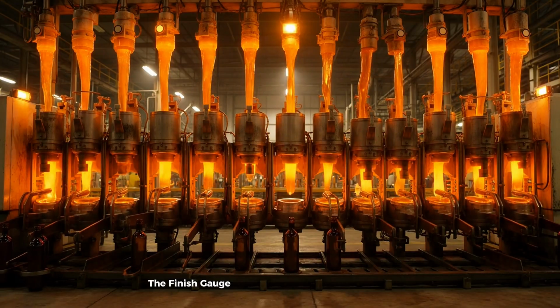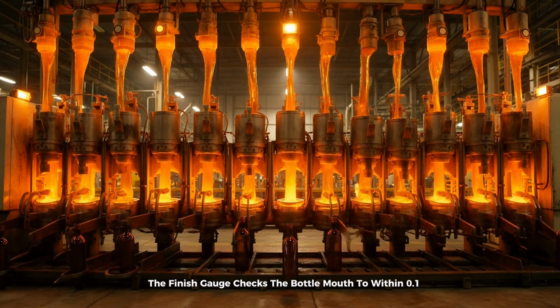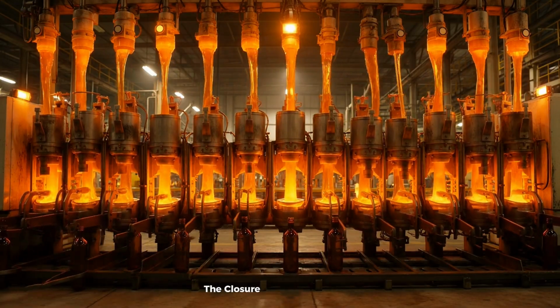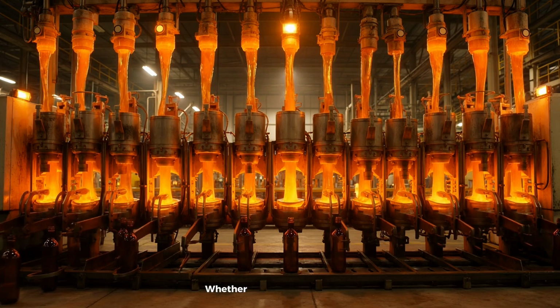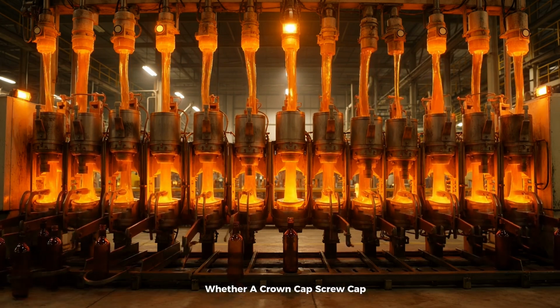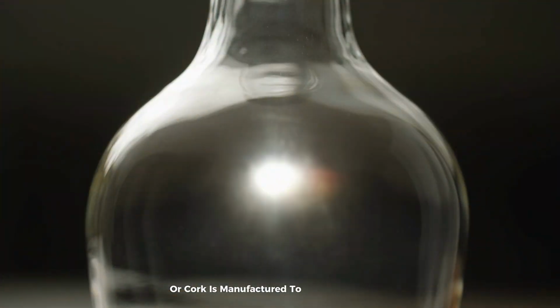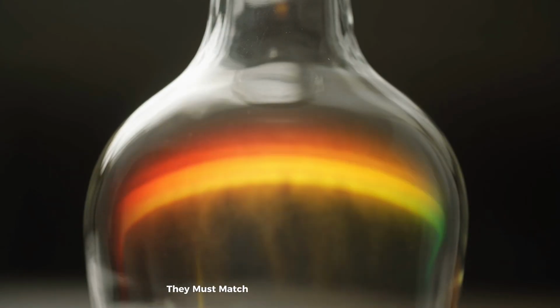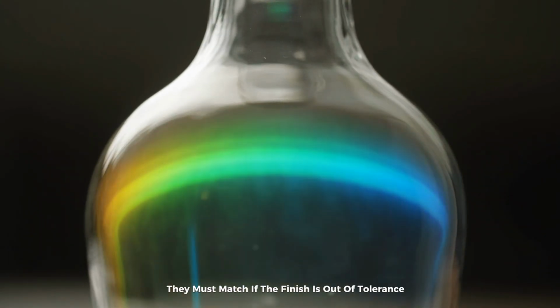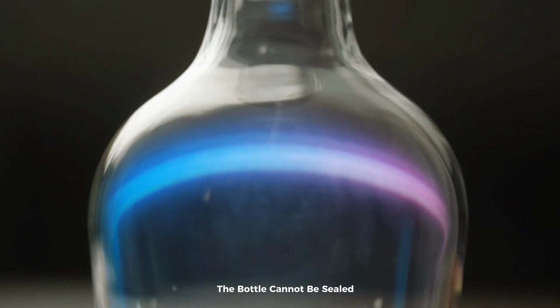The finish gauge checks the bottle mouth to within 0.1 millimeter. The closure that seals this bottle, whether a crown cap, screw cap, or cork, is manufactured to the same tolerance. They must match. If the finish is out of tolerance, the bottle cannot be sealed.